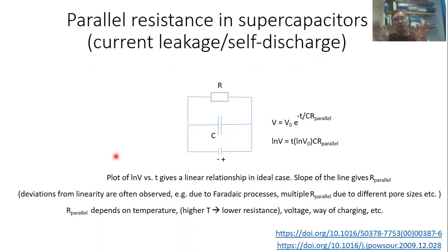When you charge a supercapacitor, it will not hold these charges for an infinitely long time in an open circuit, but it will self-discharge at a certain rate, because statistically charges can also go across the electrolyte from one electrode to the other.